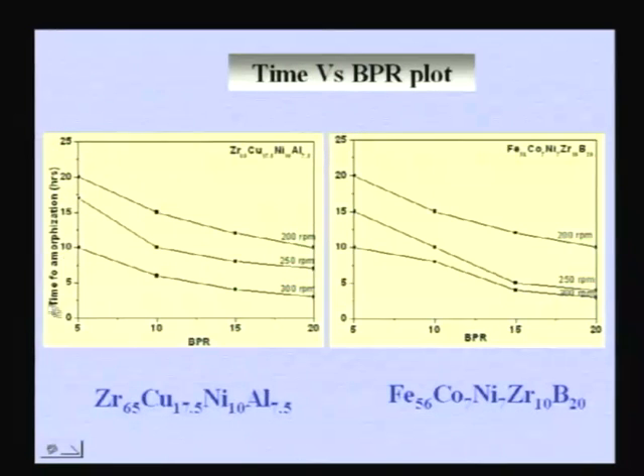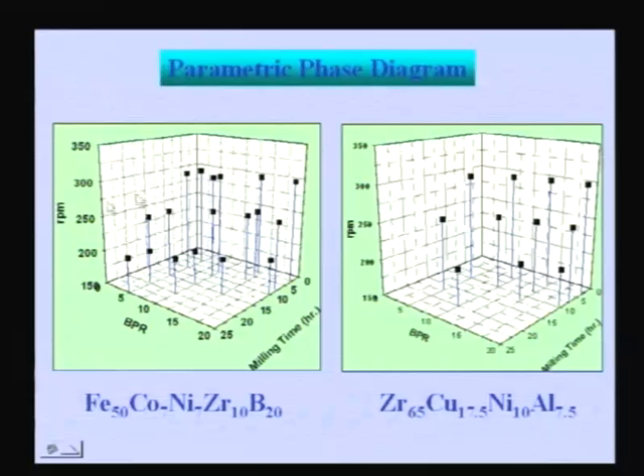This is one such example where you can see the time required for amorphization keeps on decreasing as you increase the speed, 200, 250, 300 RPM, and as you increase the ball to powder weight ratio, and this is for two different systems. And similarly, one can put the RPM, ball to powder weight ratio, and the time required for amorphization, all of them together, and see basically similar results.